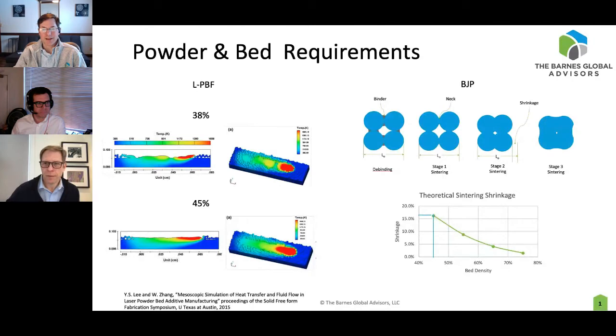Yeah, I'd say that, other than that, you have to get to a very high temperature usually for sintering. So the way I think about this problem is that the requirements for sintering are usually the finest powder you could possibly get in order to reduce the temperature and time for sintering, right? And what do we all know about fine powder? It doesn't flow. It loves moisture. It's tough to fill a bed with very fine powder. That's right. Yet, if we really want to sinter at a reasonable temperature and reasonable time, then we're going to